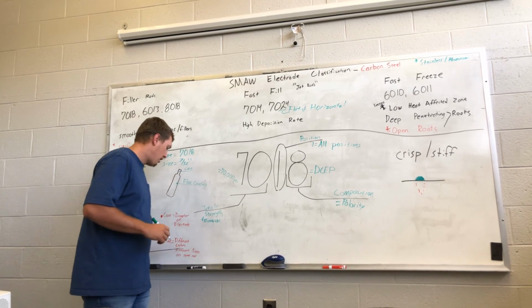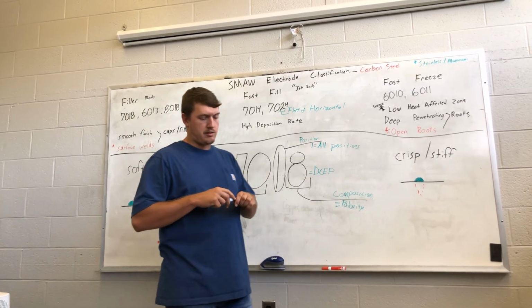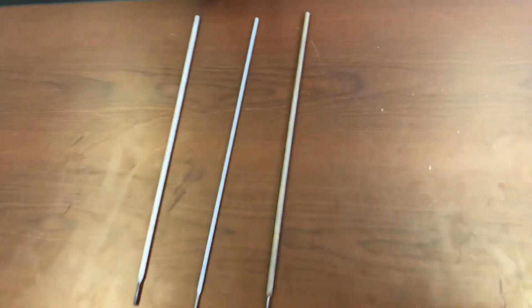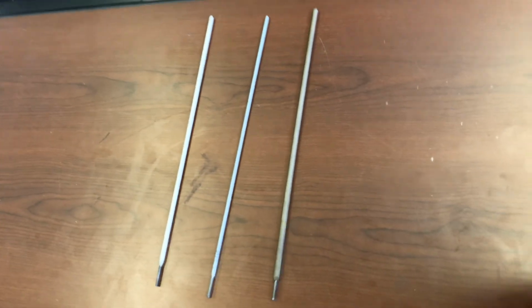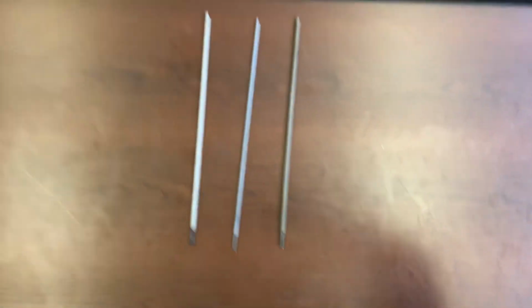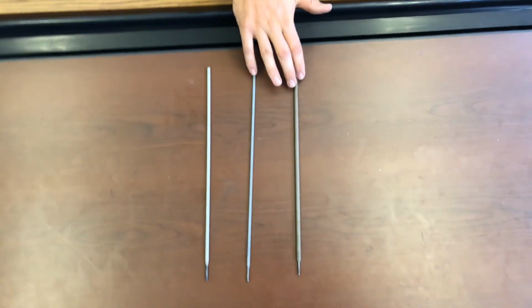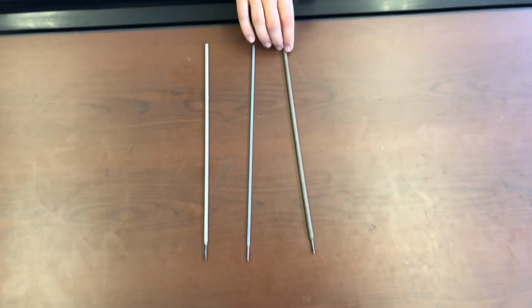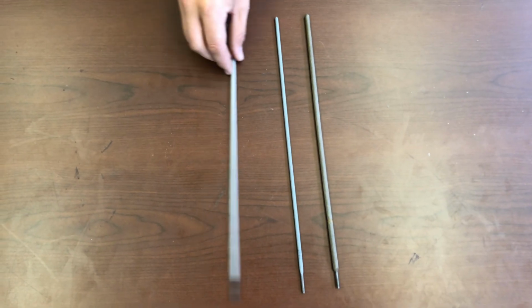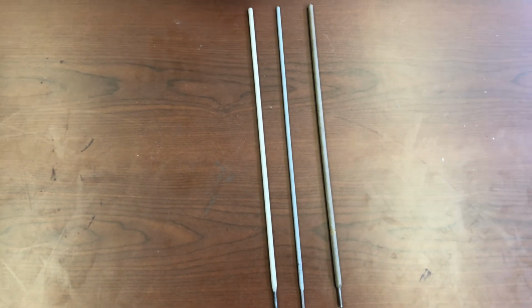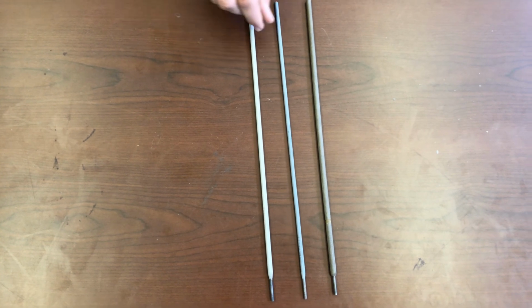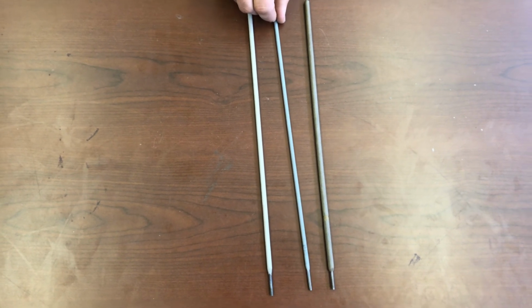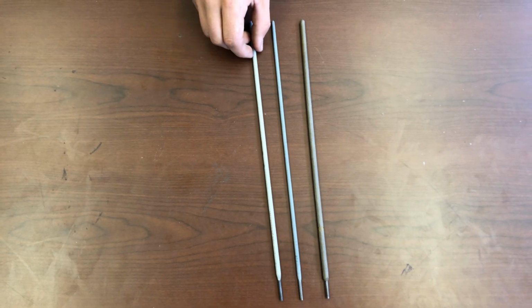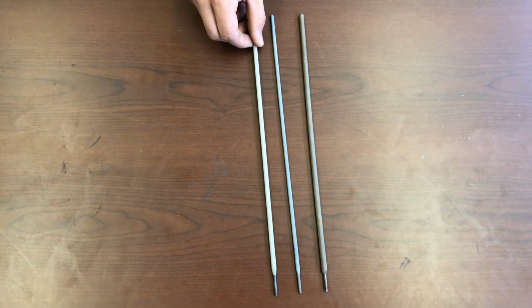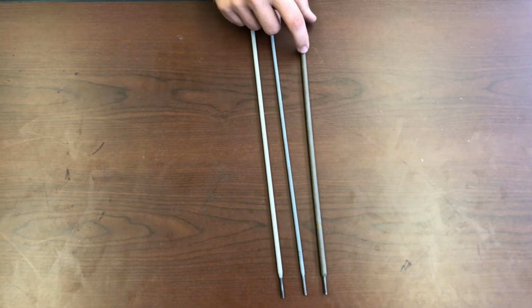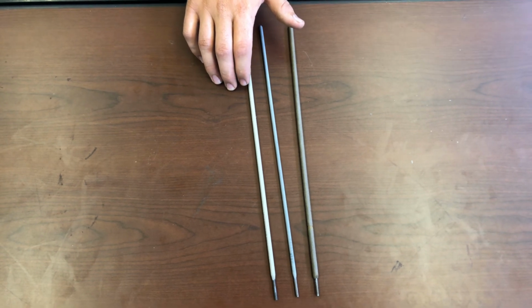Let's look at some different rods that have the same size diameter, the same size core, but different fluxes. All 3 of these rods have 1/8 diameter cores, but they have different fluxes. Here we have a 7024. You can see it has this brown flux, and it's a lot bigger than the rod beside it. This one in the middle is a 6010. A 6010 doesn't have a big flux and doesn't produce a lot of slag. Then we have a 7018. It's a 1/8 7018, but it's got a lot more flux than a 6010, though not nearly as much as a 7024. So it's going to produce a pretty good bit of slag, but not nearly as much as a 7024 would.